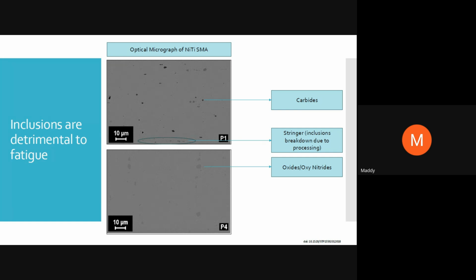If you see the elliptical region that I have highlighted, that's actually a stringer. That's because the inclusions have broken down as you continue to process them, from hot working to cold working and back and forth. So these are some of the key things that one needs to look at and understand whether the material is going to perform well or not. It will give you an indication. So people actually characterize the inclusion size and the area fraction, and they tell it in their specification. Even ASTM F2063 also calls out for this, but that's only on hot rolled products. There is no specific information on cold rolled or cold worked material, and that's what is critical. Okay, so I will leave it at that, but this is just to show you the different types of inclusions that are recognizable from your optical image. Next slide, please.